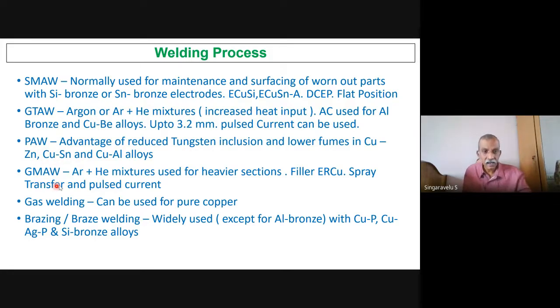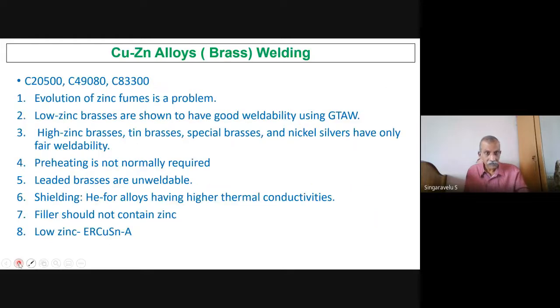GMAW can be done. Argon plus helium mixes for heavier sections. Filler is ERCU, spray transfer. Pulse current can be used. Gas welding is used for pure copper, no problem. Another best process is brazing and braze welding. I told you, except for aluminum bronze, they have been used with copper phosphorus. All the alloys you can do braze welding, right? Copper-zinc alloys, some alloys you can see, C20500, C49080, all those things.